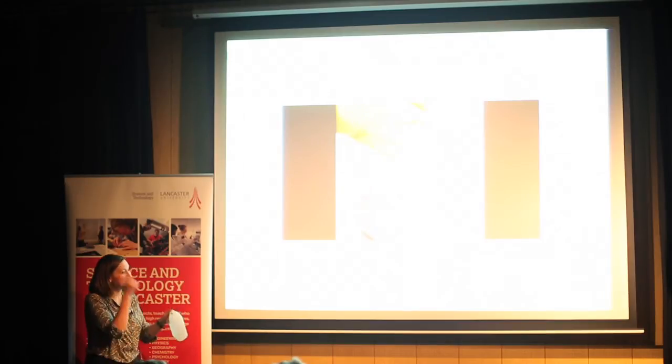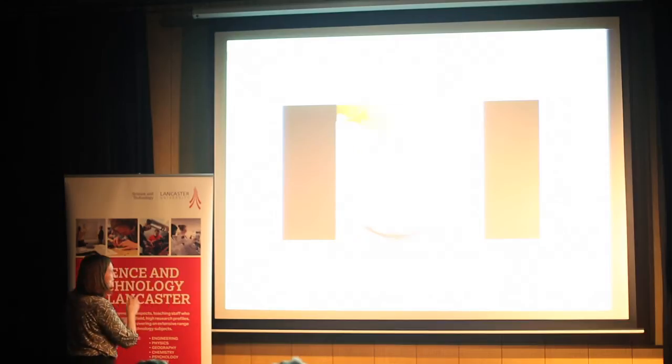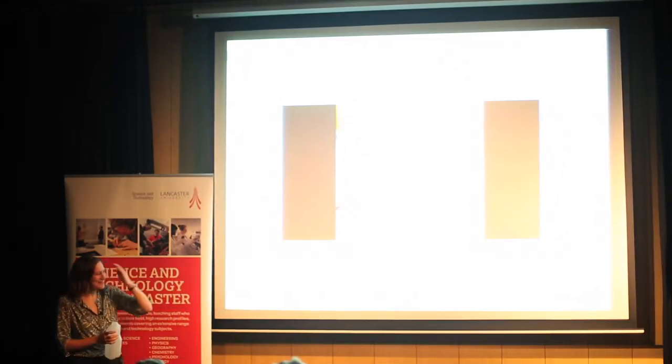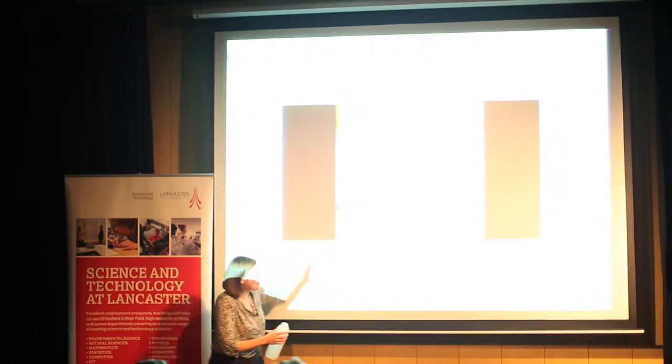So what you should be able to see is as I hit it, then it smashes, it shatters, because it's at this glassy state, it's below this glass transition temperature. There you are. Jumping back and forth here. Should have bought some liquid nitrogen here. Oh, look at that. Paused on the shot. You can see there's a small piece which has shattered off here and shattered there.